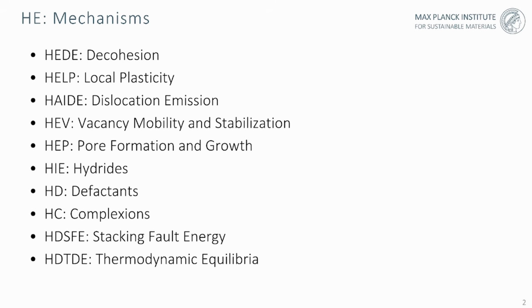In some alloys, it has even been argued or shown that complexions can form. These are interface-stabilized phases that alter the behavior of the material when hydrogen is present. In many alloys that are close to phase transformations, such as certain nickel alloys or certain austenitic steels, the influence of the hydrogen on the stacking fault energy can also play a very big role, because it would then alter the behavior of twin formation and of stacking faults. Generally, it must be appreciated that the presence of hydrogen also alters thermodynamic equilibria, because hydrogen is, after all, an alloying element like any other element in the periodic table, and hence the Gibbs free energy curves and their tie lines can be affected.